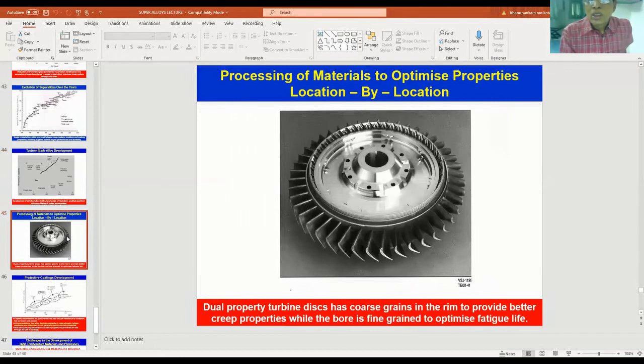Here you can see the processing of materials to optimize properties location by location. Here you have the turbine disc. The turbine disc is a dual property disc. What we require is better creep resistance in the rim, and then in the bore we require LCF resistance. Now you look at that, both these properties have to be combined. You have to produce coarse grains in the rim and fine grains in the bore. So this has been achieved, and the work has been done at DMRL, and that is the disc that has been produced, shown to you.